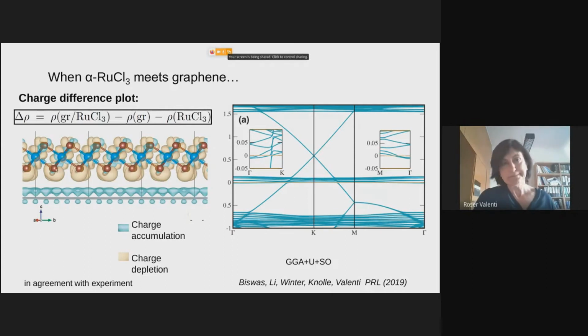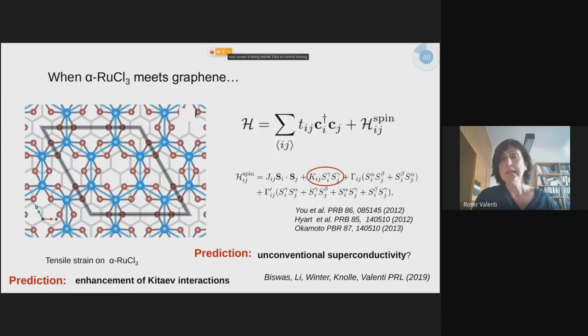And moreover, we are also influencing this ruthenium trichloride in the following way, because there is a strong mismatch between the two layers, the graphene and the ruthenium trichloride. You see the lattice of the graphene and the lattice of the ruthenium trichloride. So what happens with putting these two heterostructures together is that there is a tensile strain acting on ruthenium trichloride. And this tensile strain basically improves upon the Kitaev interaction and makes the other interactions, in fact, very small. So we are going in this direction of spin liquid.